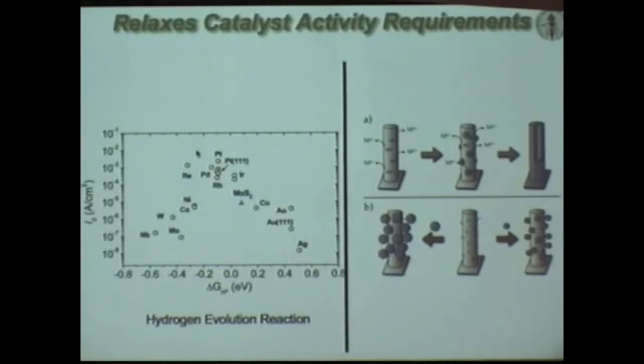The other important point is that the solar photon flux hitting a plane doesn't change. But if you take something like this high aspect ratio structure and decorate it with catalysts, if you make a fuel cell, you need to use platinum. It's the best catalyst out of all the known ones at all pHs, known in this volcano curve for 50 years, because you need an amp per centimeter squared. But the solar photon flux is only worth 20 milliamps per centimeter squared.